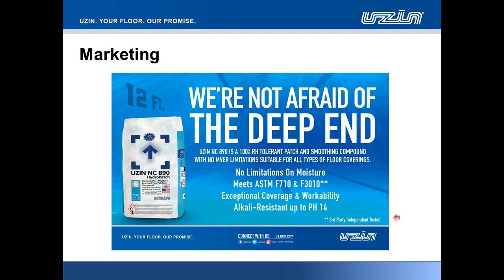The project was to develop a moisture-resistant compound with one target: to ensure that moisture will not have any detrimental effect on the patch over the long term. And what can happen to a patch when it's subjected to high amounts of moisture? Well, one thing about the patch is its compressive strength. It can stop developing compressive strength. It can also start losing compressive strength, and we didn't want any of those things to happen. Another important thing about a patch is its ability to bond well and develop bond strength, and again, not lose it when it's subjected to moisture.